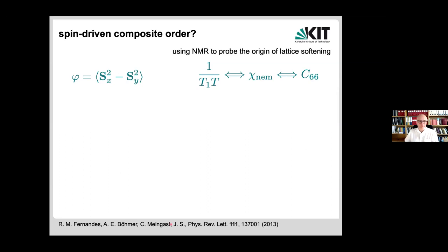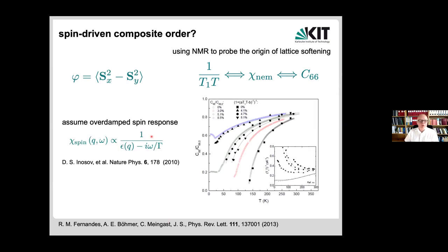And in a work with Anna Böhmer and Christoph Meingast and Raphael a number of years ago, we made one specific assumption, otherwise you really can't make this work, about the spin dynamics that was seen in neutron scattering data. And we could indeed make a connection between the elastic constant data, which are the lines shown here measured by Anna and Christoph, and existing NMR data, and there's really not much fitting going on here. You can make a one-to-one correspondence between magnetic fluctuations driving the lattice softening and the lattice softening itself. There are other iron-based systems where this doesn't work quite as beautifully, but it does work very nicely in these barium 1-2-2 systems that I've been showing you the phase diagram on earlier.